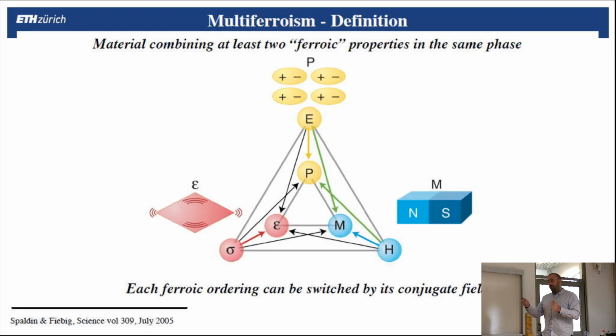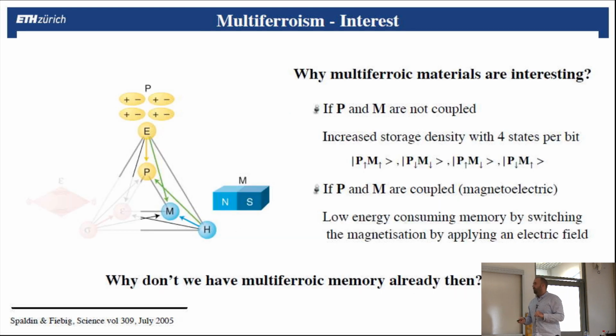So now, ferroelectricity, ferromagnetism, let's go to multiferroism. Here you can recognize the three pictures I showed in the first slide. Let me, from now on, forget about this part and just concentrate on these two parts. A material combining at least two ferroic properties, so polarization, magnetism, or ferroelasticity, in the same phase is called a multiferroic. And each of the ferroic orders, for example polarization, can be switched by the conjugate field. So polarization you can switch by applying an electric field, and magnetization you can switch by applying a magnetic field. But there is also a cross interaction. In some cases, you could influence the polarization by applying a magnetic field, or the other way around, by applying an electric field, you could change the magnetization.